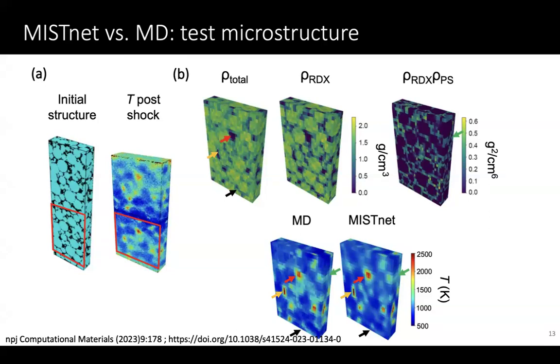The other important thing to say is, you probably know that for AI, you need a lot of data, and you do. This doesn't mean in this particular case that I need 1,000 simulations. We could get away with about a dozen simulations because one simulation has a lot of information. One simulation samples all sorts of local environments, different voids, interfaces. So from one 3D map, you learn a whole lot, okay? We were surprised by this, but it's actually very powerful.